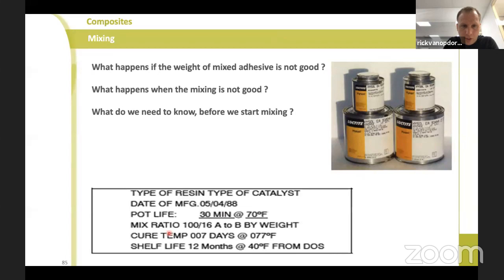What you see here is a mix ratio of 100 to 16, sorry. And that's by weight. So 100 of those is 16 of those. And it's important that you have exactly 16. If you add too much, by 1 or 2 grams, you can already have an exothermic reaction. That means it will burn up.